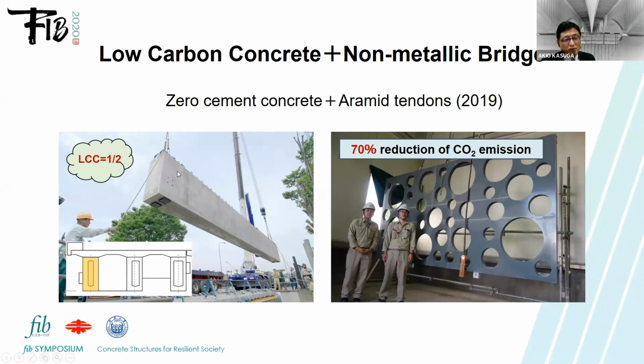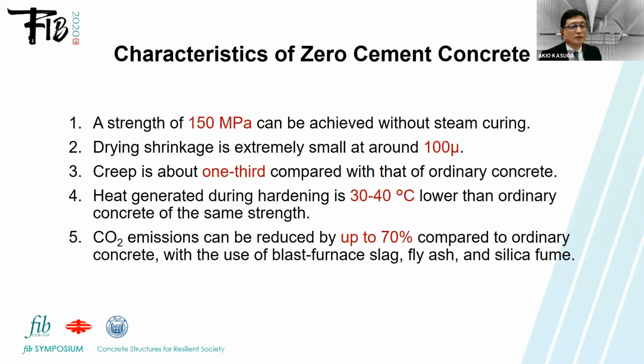So zero cement concrete is a very new material, and compared with ordinary concrete, we can reduce CO2 by up to 70%. These are the characteristics of zero cement concrete. We can get about 150 MPa, very high strength concrete, without steam curing. At the same time, the drying shrinkage is extremely small, around 100 micro. The creep coefficient is about 1/3 compared with ordinary concrete. The heat generation during hardening is about 30 to 40 degrees centigrade, much lower than ordinary concrete. And as I said, CO2 emission can be reduced by up to 70% with zero cement concrete.